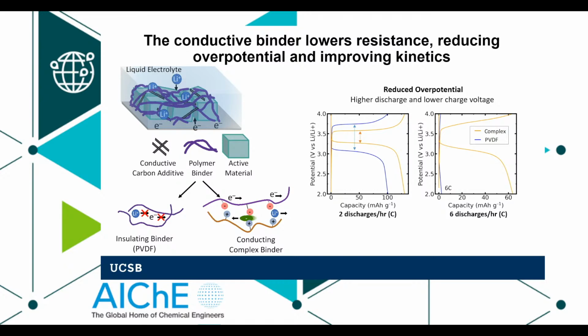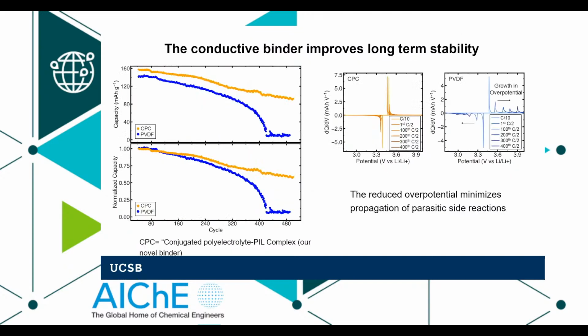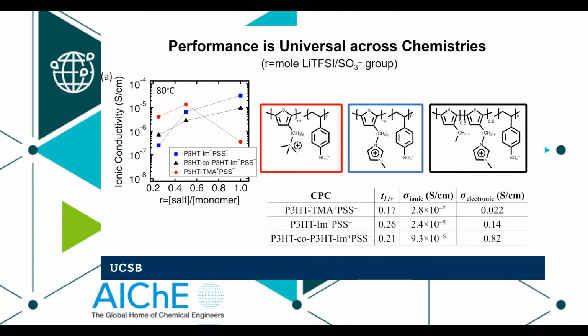And so that's true at 2 charges or discharges per hour. At 6 charges or discharges per hour, PVDF stops working altogether. It's just not stable. It has to run at such high overpotentials, the whole thing degrades, whereas the complex keeps going. The result is that if you look at capacity as a function of time, these batteries with the coacervate binder are able to last for a very, very long time because we're probably running them at much lower overpotentials, so we have fewer of those parasitic side reactions.